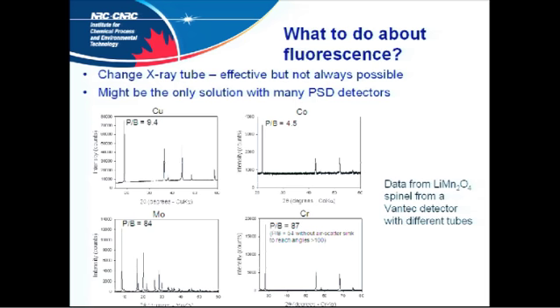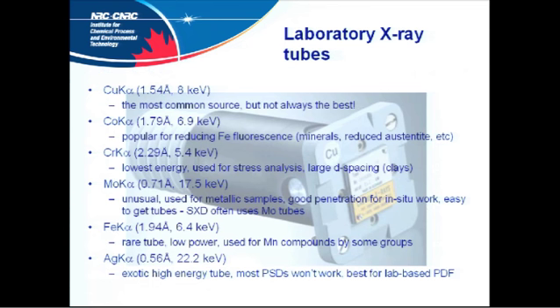So I'm having to take some steps for the people who are doing cobalt systems to try and reduce this problem. Moly may not be very common, but that really avoids a lot of the problems. Chrome is a bit of an oddity. It's one of the ways around it, and you can get particularly good data from a manganese sample, but again, there are compromises involved. Your low resolution in terms of d-spacing starts to suffer.